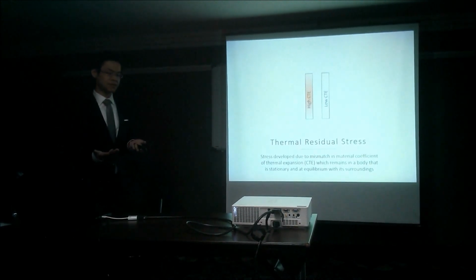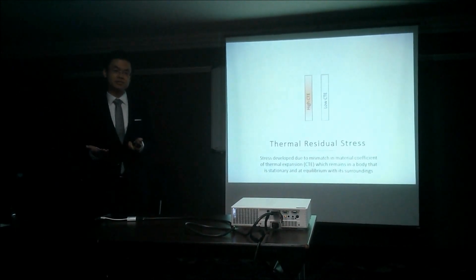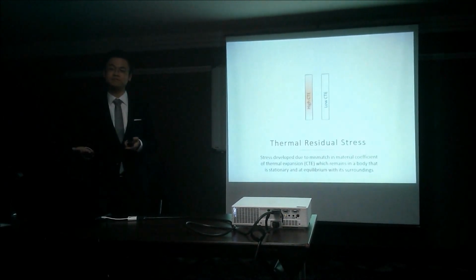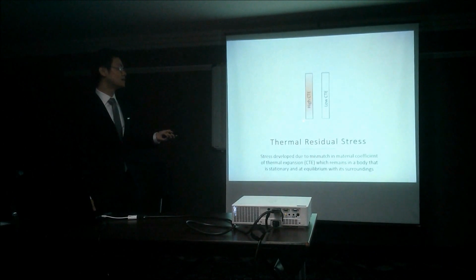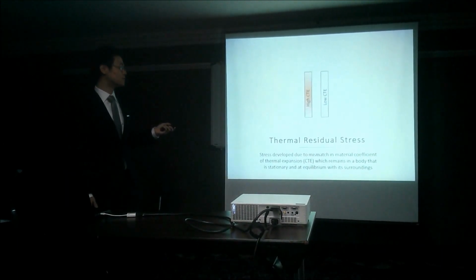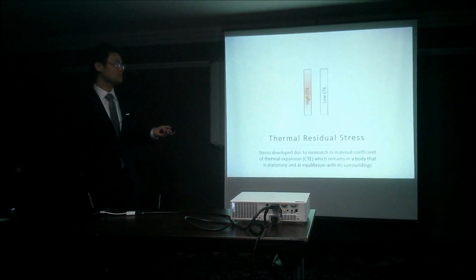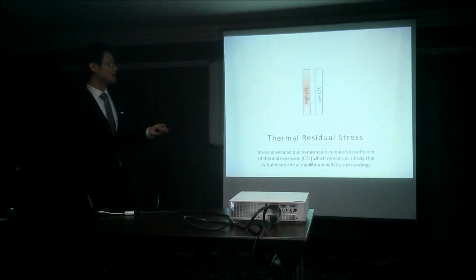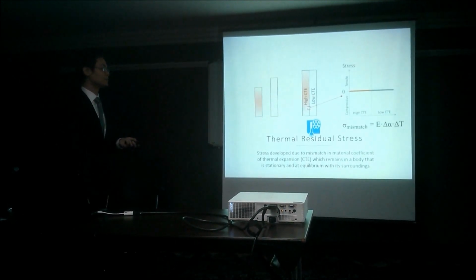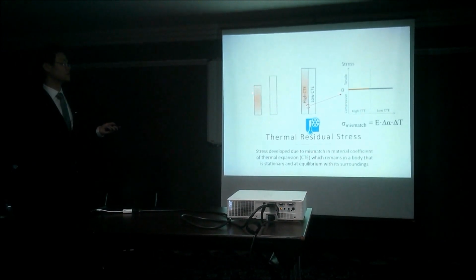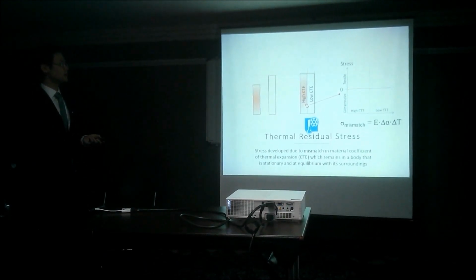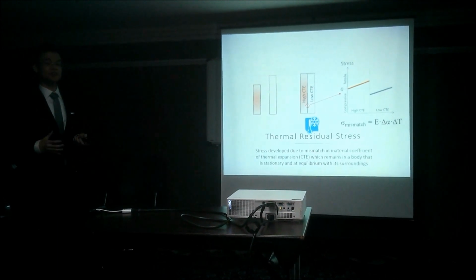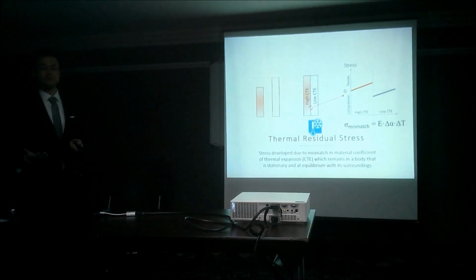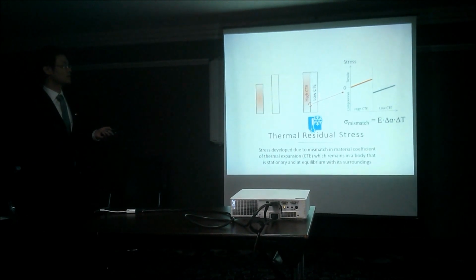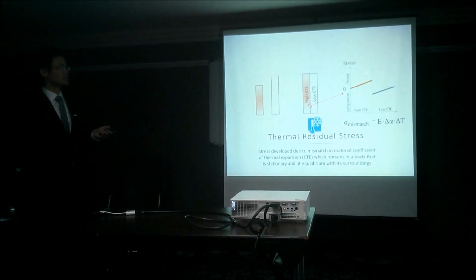Now, in general, for spray formed materials, the residual stress is caused by thermal stress during cooling. And thermal stress is caused by the mismatch in the materials' coefficient of thermal expansion. Let me give you an example. What if we bond a high CTE layer with a low CTE layer and cool it down? For reference, let's have the individually cooled lengths on the screen. Now, during cooling, the high CTE layer shrinks much more than the low CTE layer, but it is now constrained by this layer, causing a tensile stress in the region.